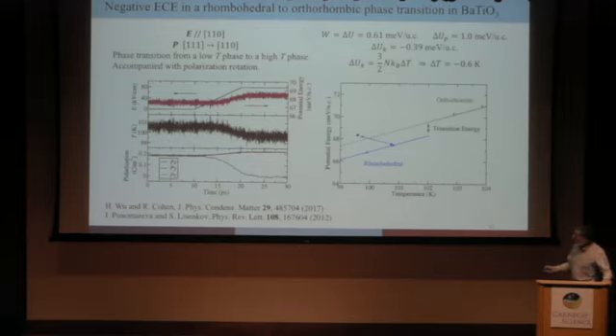Here is the electric field in kilovolts per centimeter, and you see for some time it's zero. There's actually quite a lot of equilibration before zero, but at some time we start to increase the electric field. Can you see? Going up linearly, there's a linear ramp, and then we leave it at some finite value. And the potential energy actually goes up. So this is what I was saying to you. This is a negative electrocaloric effect.